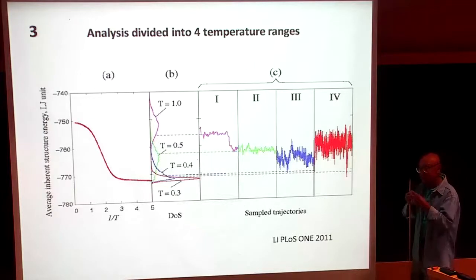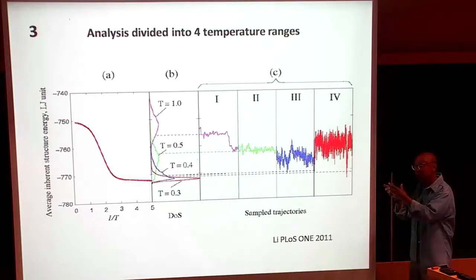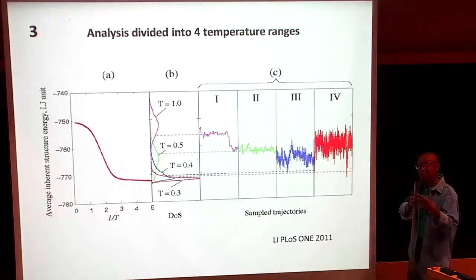Namely, the kind of mechanism, the kind of atomic rearrangements that take place during one of these hopping events is exactly what you have. There's some cooperativity there in the way of chains for the fragile glasses. We did the same thing again for the strong glasses. It's not so much chains anymore, it's bond swapping.